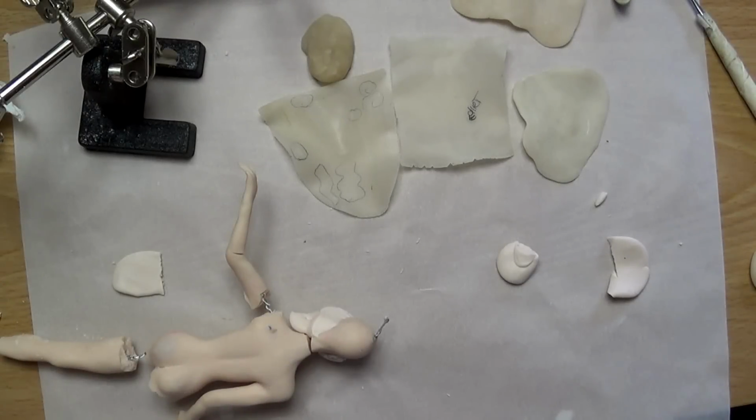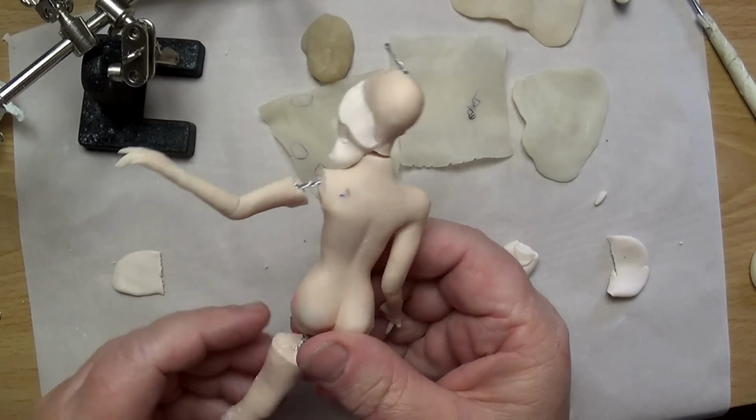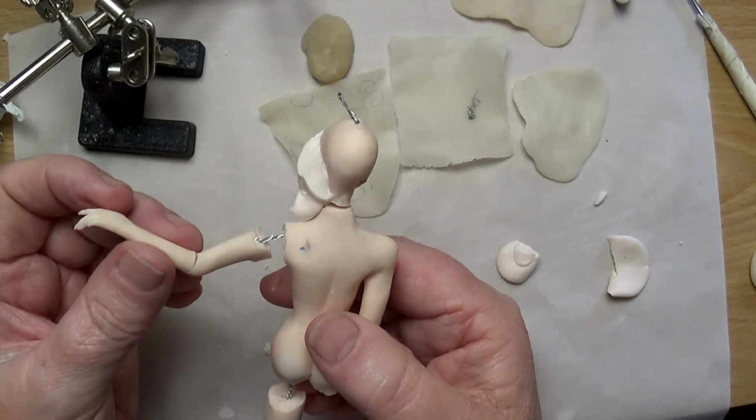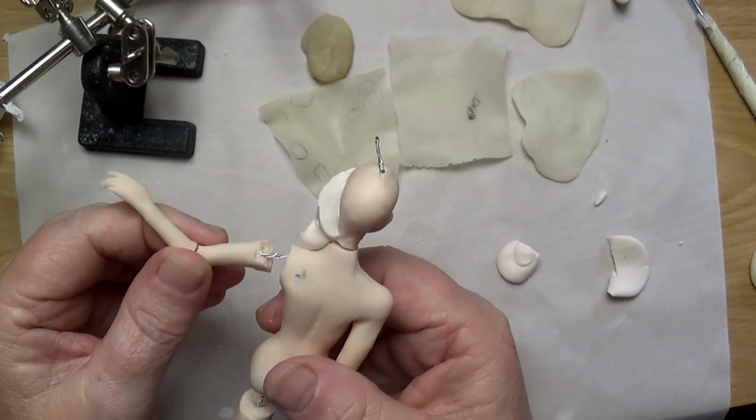This next one took me a little while to figure out, but I live in an area that has a lot of humidity and we do have dampness. I also live out in the country, so I have a lot more of this than other people may have. Now, it just never clicked with me that a climate would have anything to do with it. My thinking just was not going in that direction. I kept thinking it was me that was making the problem, when I found out the problem was the climate that we live in. Polymer clay, I found, does not like moisture whatsoever or dampness. I had to invest in a dehumidifier, and I put it in my studio, and I had no problems whatsoever. Even with the air conditioning running, I still needed the dehumidifier.